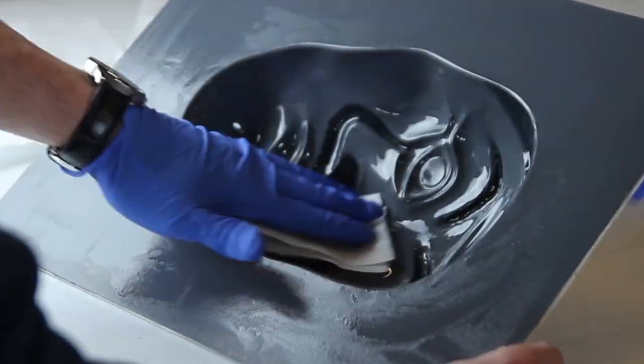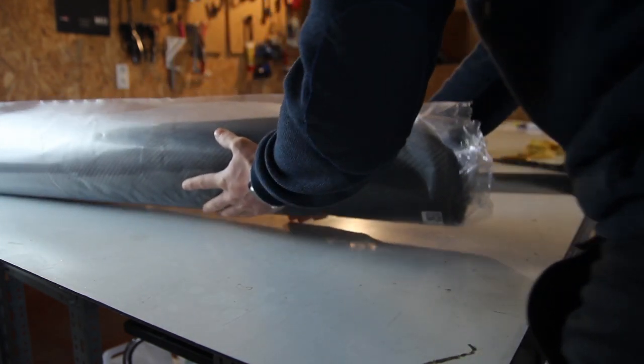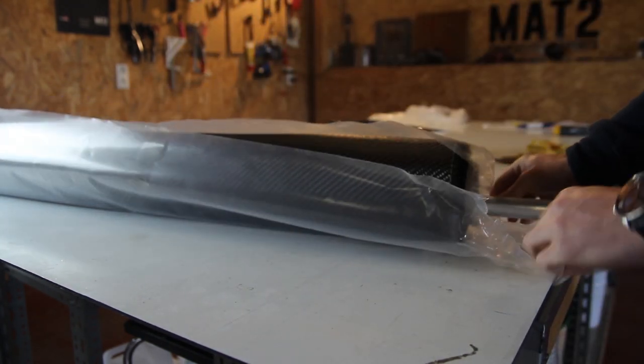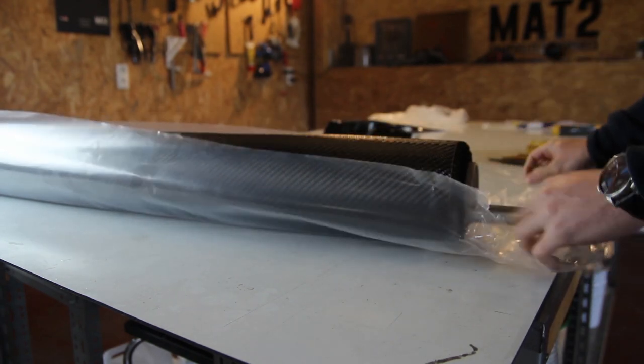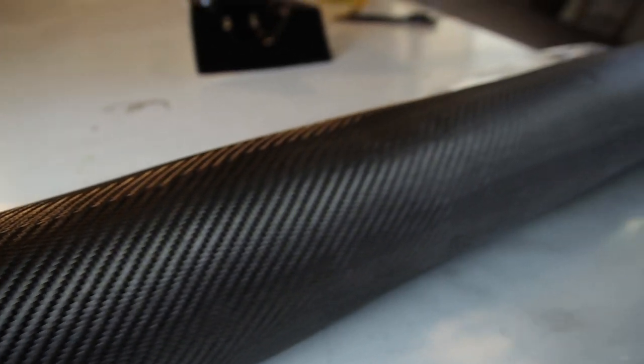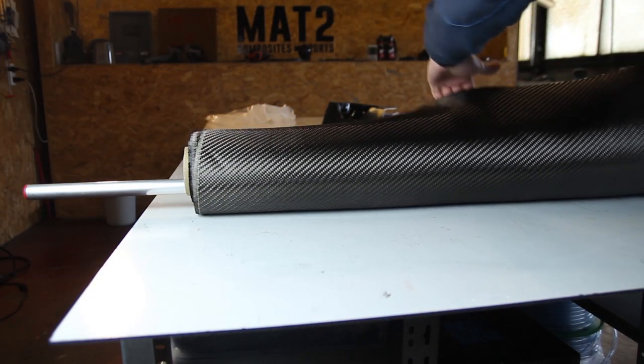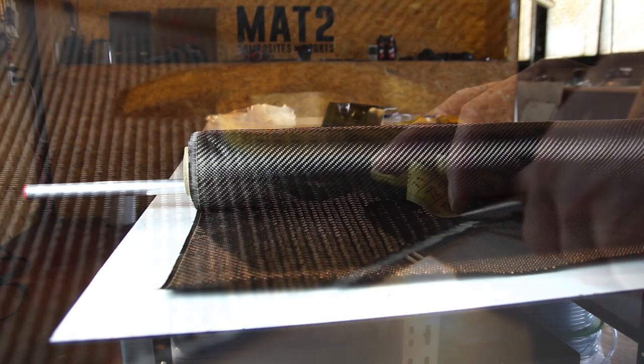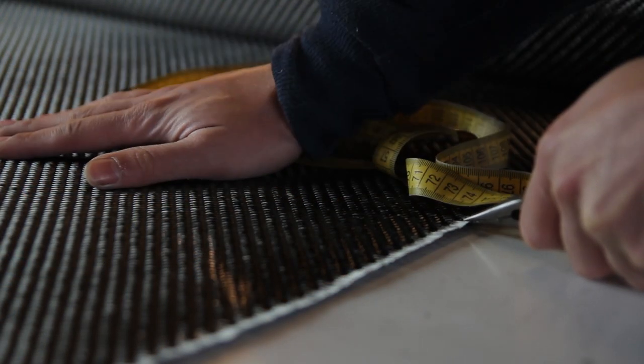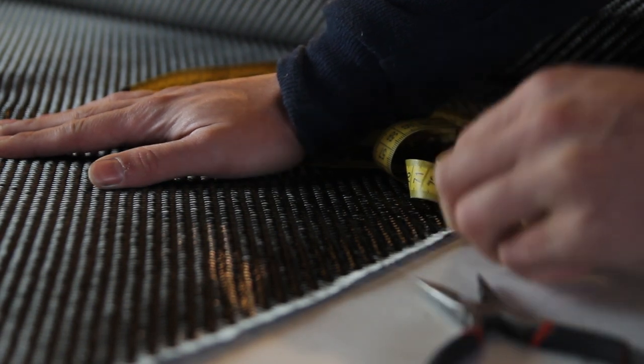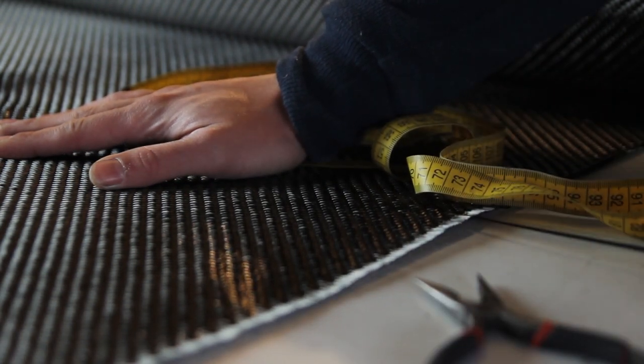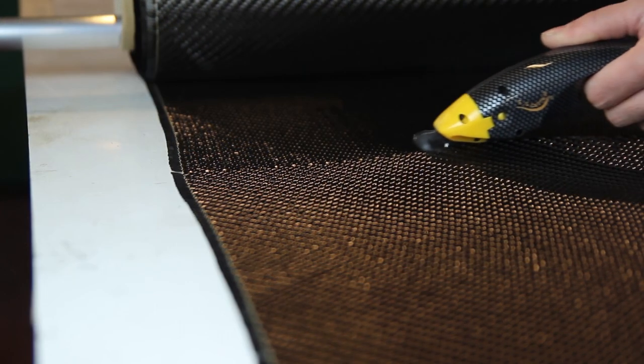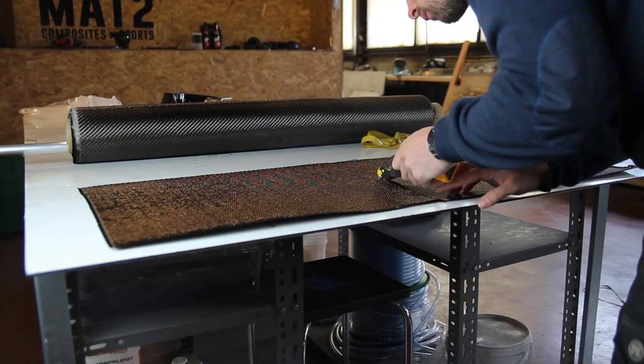And then it's ready again for five layers of Easy Lease. So it's a chemical release agent that works very well. And something extra that you should know is that once it's applied in five or six layers, for the next part you only need to add one layer just to make sure that it will remove again. So now to the carbon fiber part, so I'm using a 650 12K weave. So it's a 12K and as I have mentioned in previous videos, this is probably my favorite carbon fiber because it's quite dense so it won't leave small gaps while applying it in 3D shapes and it's forming quite well and it adds a lot of stiffness as well with one layer.